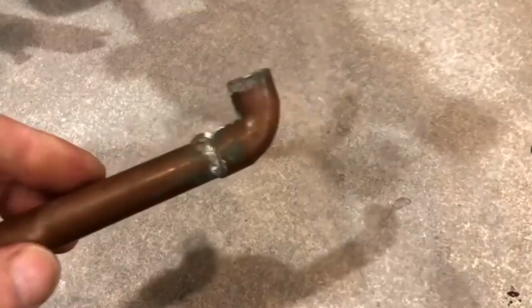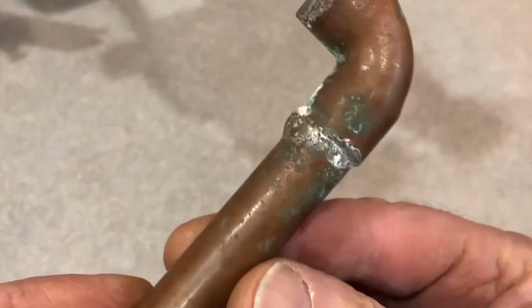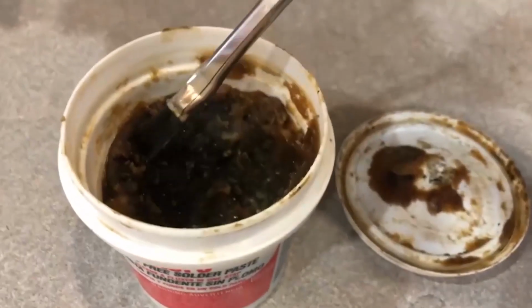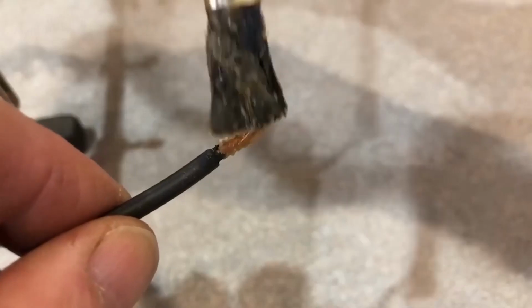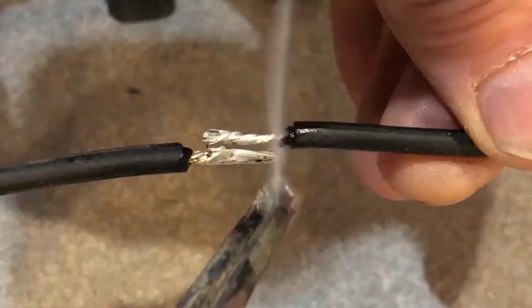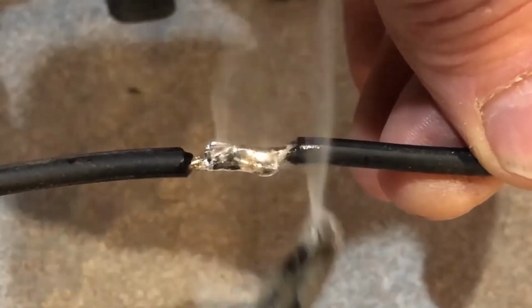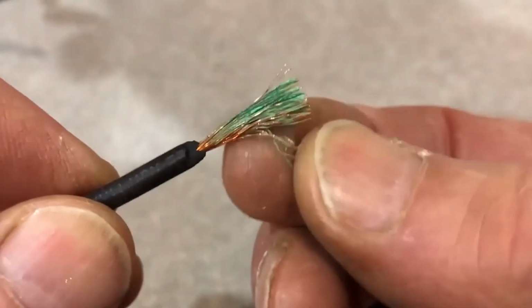This works fine, but it must be cleaned off after soldering, or corrosion from the acid will result over time. Never do this. Solder wires with acid flux. It makes a nice solder joint all right, but the flux is now leached into the wire, and over time the wire will corrode invisibly from within inside the insulation.